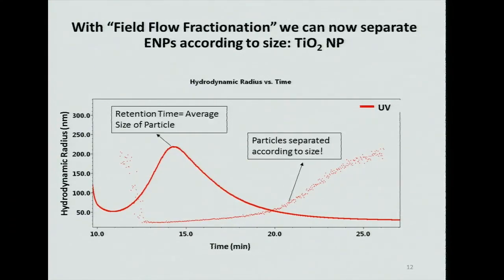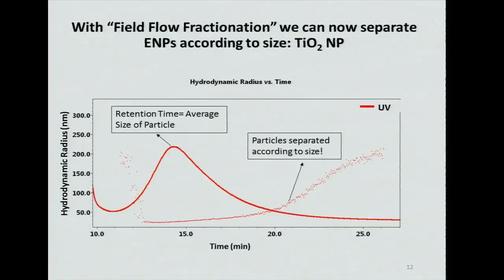So the first step was to optimize field flow fractionation to detect nanoparticles. We use titanium dioxide nanoparticles here. What I really like about field flow fractionation is that it gives you the entire composition of your sample. You see everything that there is. The peak here gives you the average size, and the little red dots give you the particle size distribution.